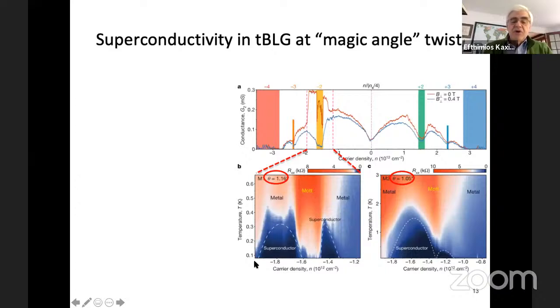So this plot shows the nature of the material. It's superconducting in this range, again superconducting in this range as you change the carrier density. So this is a blow up of this small region. And in the middle, you have an insulator. And this is at a certain angle. This is at 1.16 degrees of twist, a different angle. So this is 1.05 degrees of relative twist. Again, superconductor, metal up here, insulator in the middle, Mott insulator, and so on. So this is quite rich and interesting behavior.